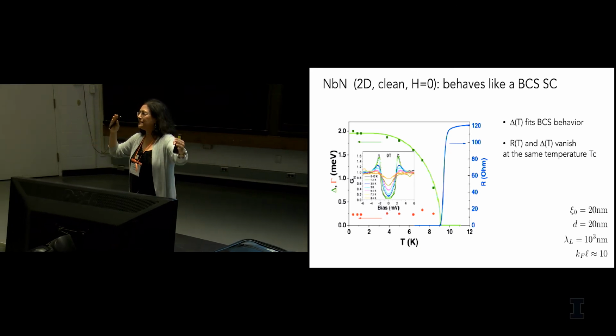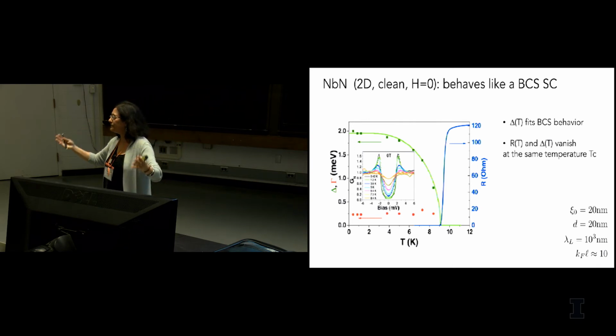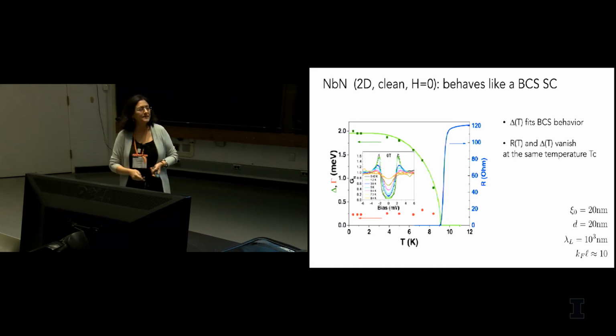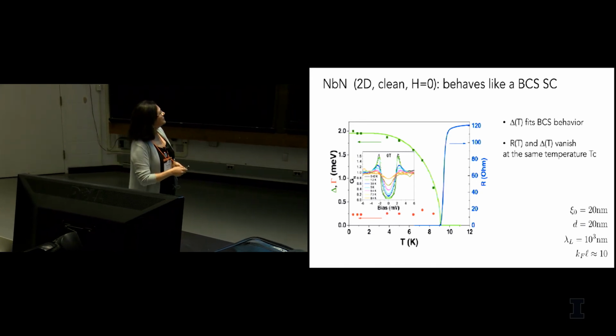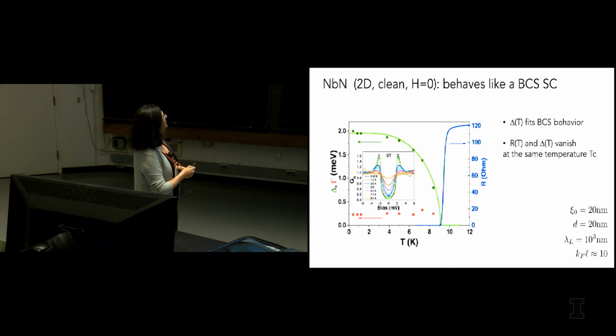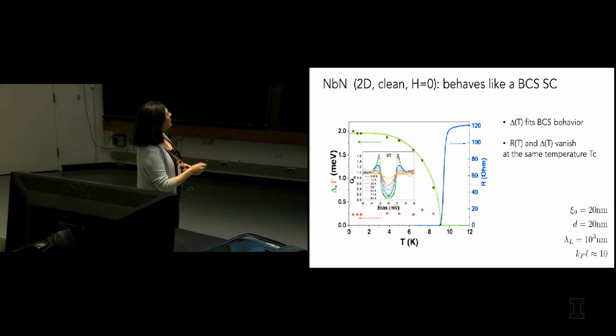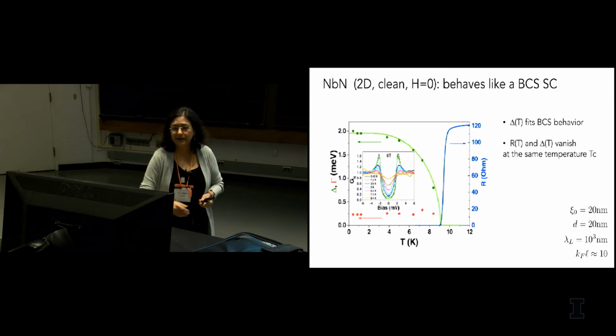Typically, the experiments in this field have been difficult to interpret because you want to separate disorder and magnetic field. And typically films have so much disorder that when you apply a magnetic field, it's difficult to separate these two aspects. But these experiments from the group at Tata Institute have taken very clean niobium nitride. When there's zero field, you can see this is clearly a BCS superconductor, with the resistance vanishing at the same temperature as the gap vanishing.